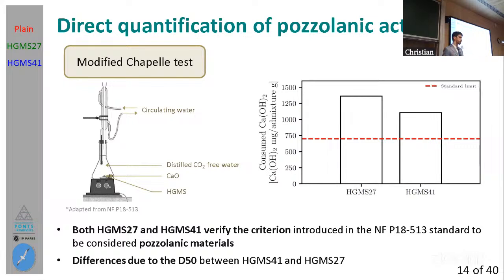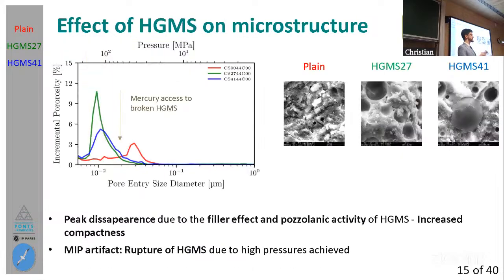So, with all of this, I tried to show you that there is some filler effect and pozzolanic activity of these two spheres, and these chemical interactions are known for improving the compactness of the material. So for this purpose, and analyzing if this compactness was increased, I show you here some MIP and SEM results. There, again, in red, the plain cement paste, in blue, the cement paste with HGMS 41, and in green, the cement paste with HGMS 27.